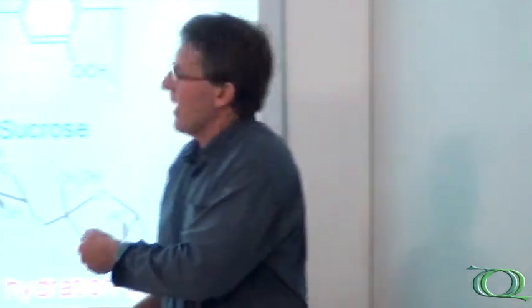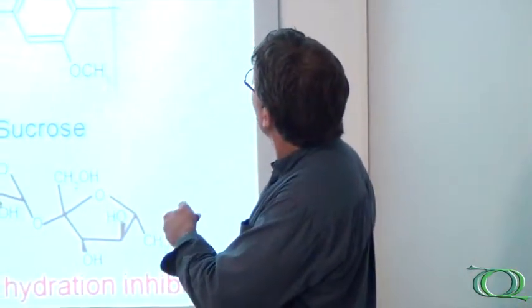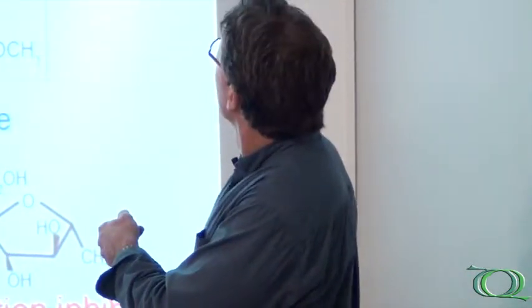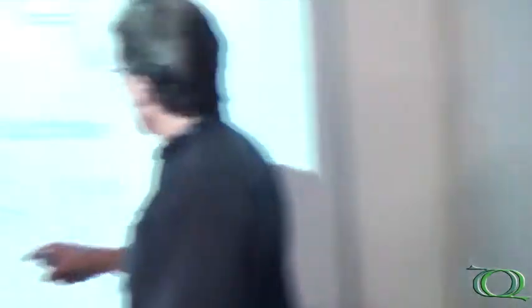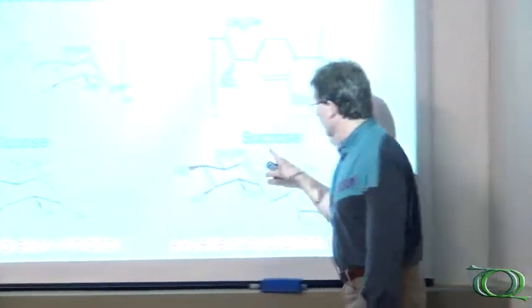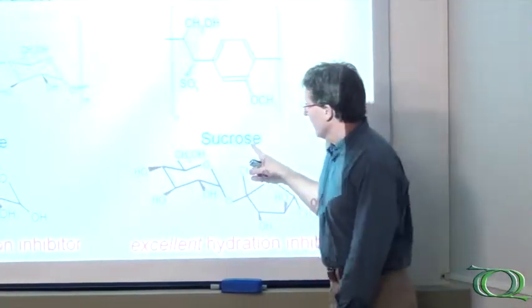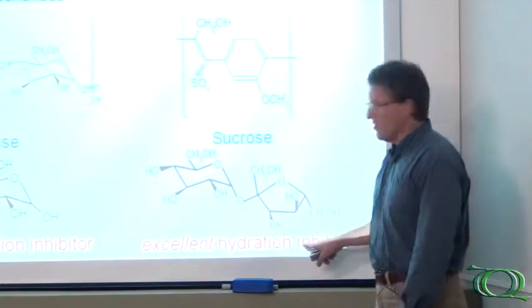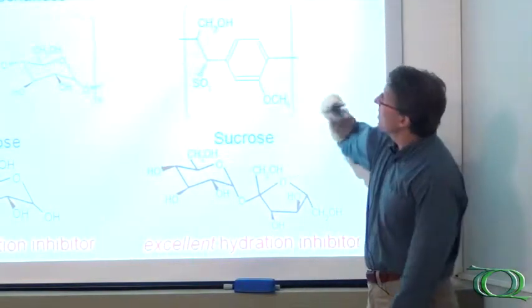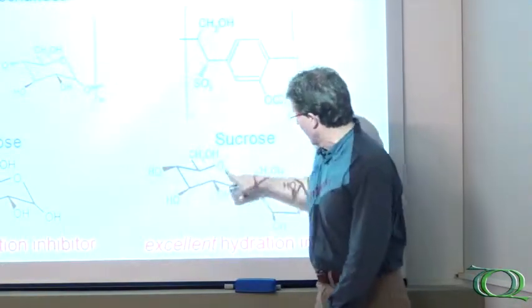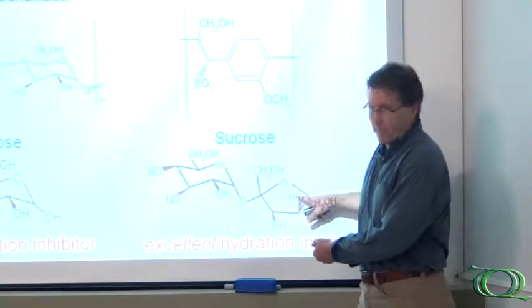And they use saccharides. And the question is, why saccharides? And how do they, what counts for these differences? Because starch, cellulose, starch basically is cellulose, carboxylate. And moreover, if we look at two model compounds that we've used, glucose is a moderate to poor inhibitor of hydration. Sucrose, of which you have a lot in Brazil, is an excellent hydration inhibitor. Like, tiny concentrations stop hydration. And it's surprising, at least it was to me, because sucrose is composed of a glucose ring and a fructose ring.